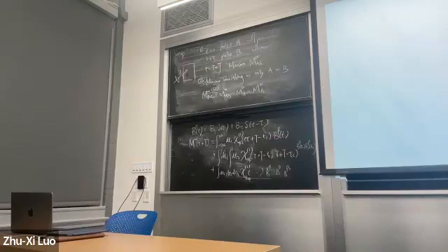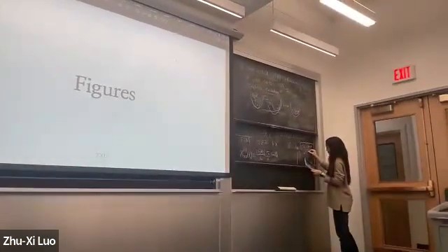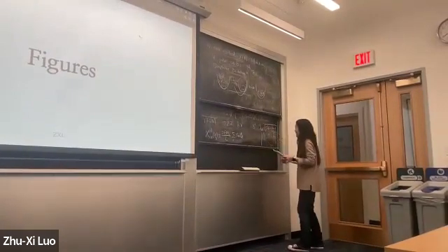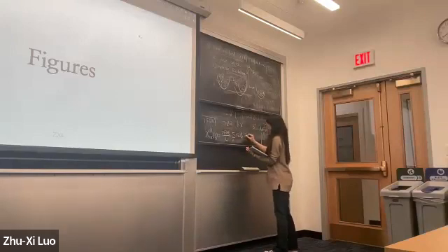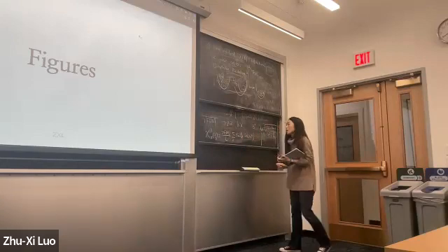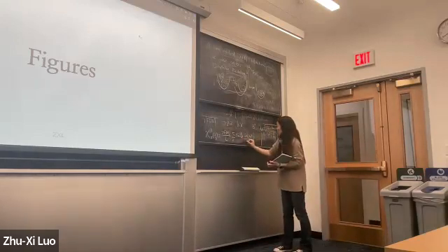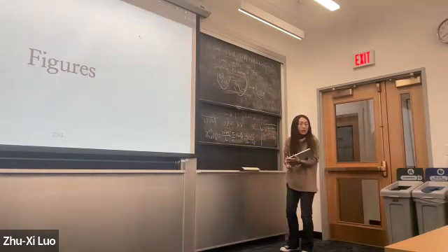Chi1, in the X direction. So you're also detecting the X direction. The response at arbitrary time can be expressed as some commutators of magnetization at different times. And in the end, the result is just a Heaviside theta function divided by system size, summation over momentum, sine squared theta k, where theta k is arcsine of minus 2J sine k over lambda k, some function of J and h and k, times sine of 2 lambda k t. So if we do a Fourier transformation, this will give you some delta of omega minus 2 lambda k. And you have this summation over k, that gives you the broad continuum.